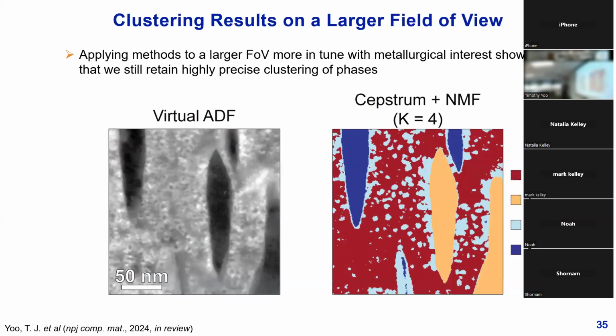And so again, going back to the original motivation for this task, we want to be able to operate on larger length scales. And so this is an application of the same exact algorithm, just on a larger length scale. This time it's about a 200 to 300 nanometer field of view, as opposed to about 150 before. And here we can see that we have nice sharp boundaries around the precipitates once again. Before we get into the actual diffraction patterns, we can see that we've automatically segregated 4 clusters here instead of 3. So there's some kind of new unique structure that we didn't know about before that's being automatically picked up by the algorithm without us necessarily having prior knowledge of particular systems.